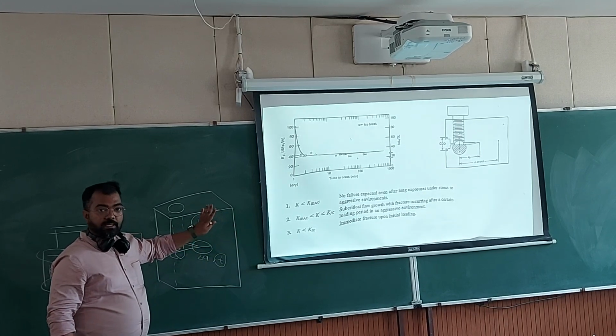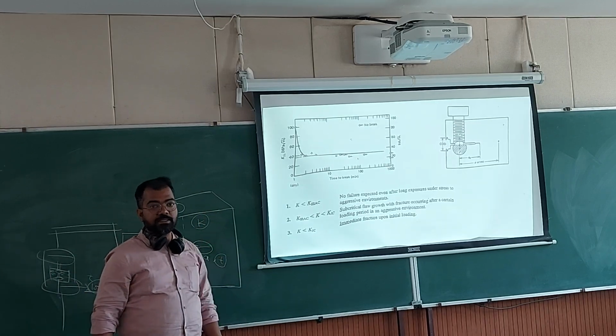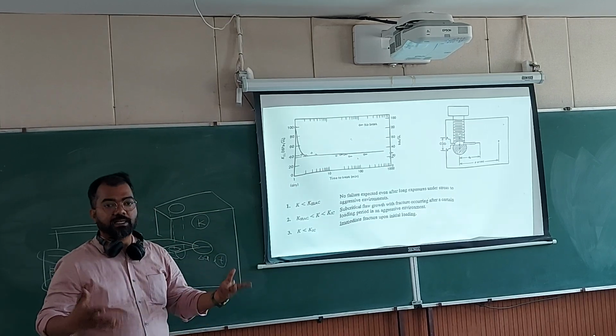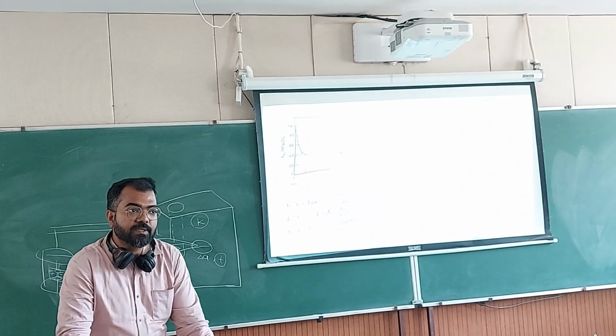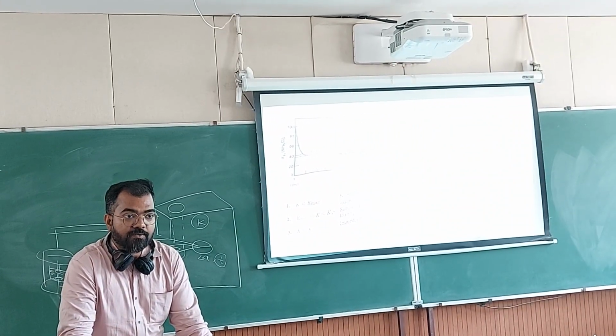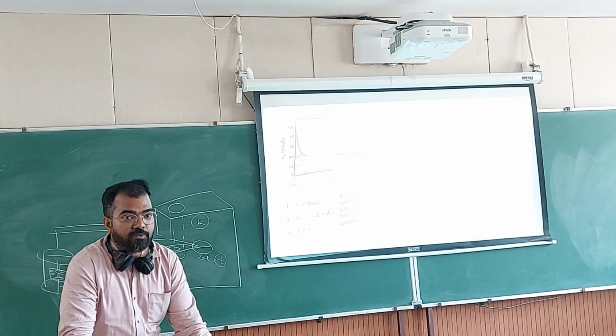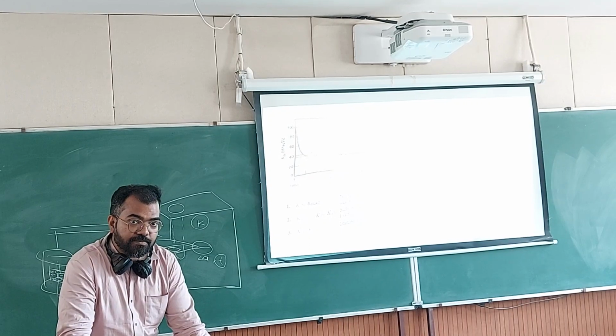The problem is, there is a problem. The problem is that how will you generate a pre-crack? This is a practical problem. How will you generate a pre-crack? In order to do a pre-cracking, you have to apply a fatigue loading. In order to have a fatigue loading, you have to have holes in it. You have to have pin loading of CT specimen. Otherwise, how will you do it?